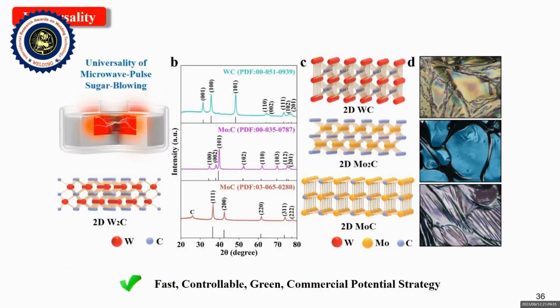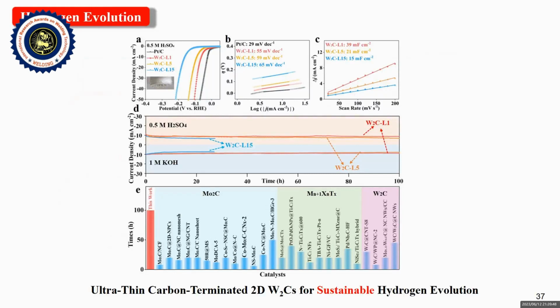Additionally, this fast, controllable, green, and commercially promising microwave strategy can prepare a variety of carbides. Due to the terminal modification of ultrathin carbon, these two-dimensional carbides can achieve suitable hydrogen evolution.